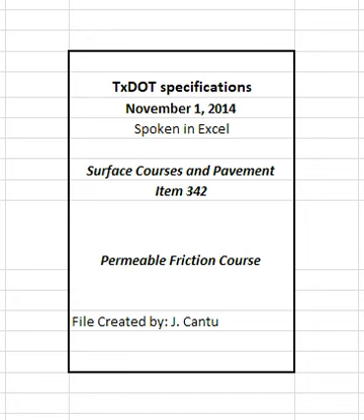4.4.2.1.13 Trial batch sampling. Obtain a representative sample of the trial batch and split it into 3 equal portions in accordance with TEX 222F. Label these portions as contractor, engineer, and referee. Deliver samples to the appropriate laboratory as directed.